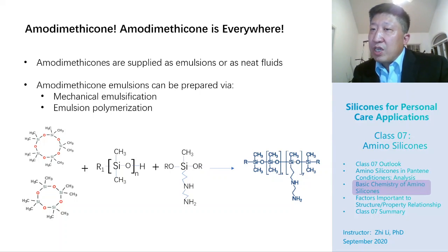silicone group. They tend to form non-covalent association along the polymer chain and restrict the mobility of the polymer chain, resulting in increasing viscosity, a phenomenon called structuring by many silicone suppliers. But once you put it into emulsion, those issues no longer exist. As long as you have enough surfactant, you're going to have very stable raw materials over a 1 year shelf life easily.